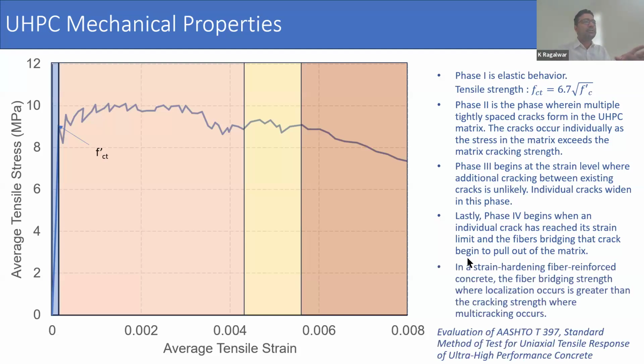But this uniaxial tensile behavior also leads to varied flexural behavior, which we'll see in the next case, depending upon whether the behavior under uniaxial tensile test is strain hardening or strain softening. So in a strain hardening concrete or fiber reinforced concrete, basically the fiber bridging strength where localization occurs is greater than the cracking strength. So this localization maybe occurs here, because we don't see the tensile strength increasing again. If it is higher than the first cracking strength, then you would see multiple cracking, and it is known as strain hardening.